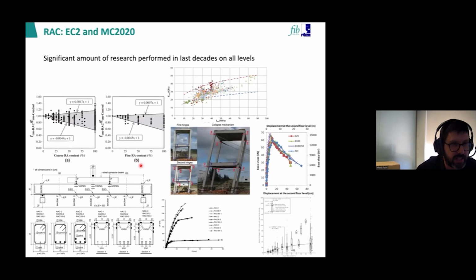But of course, recycled aggregates having this residual mortar that we aim basically to decrease presents some challenges, right? Mix design, we said, and then effects on concrete properties that, if we were to generalize in the most general way, we would say the more recycled aggregate we use, the more reductions in properties we will see. Loss in compressive strength, modulus, shrinkage, creep, and so on, especially if we move from coarse to also fine recycled aggregate, that is recycled sand. And you can see here basically some tendencies of how much we'll be losing compressive strength.